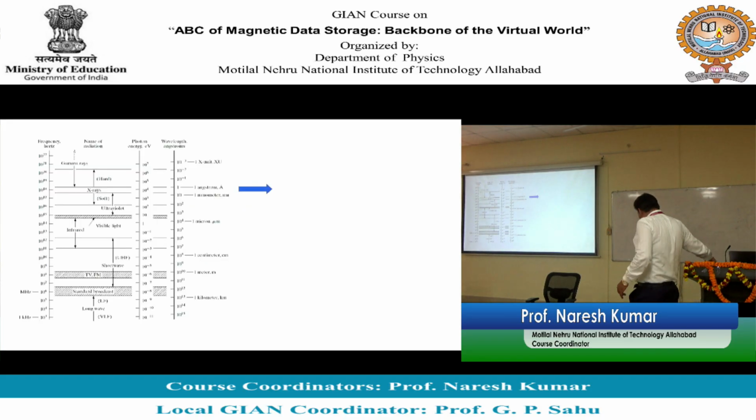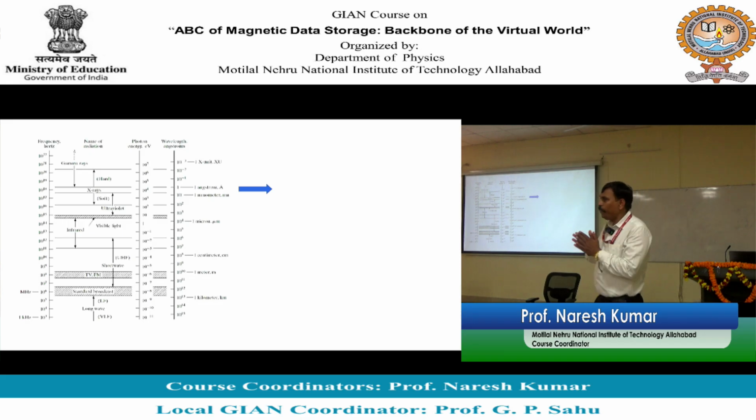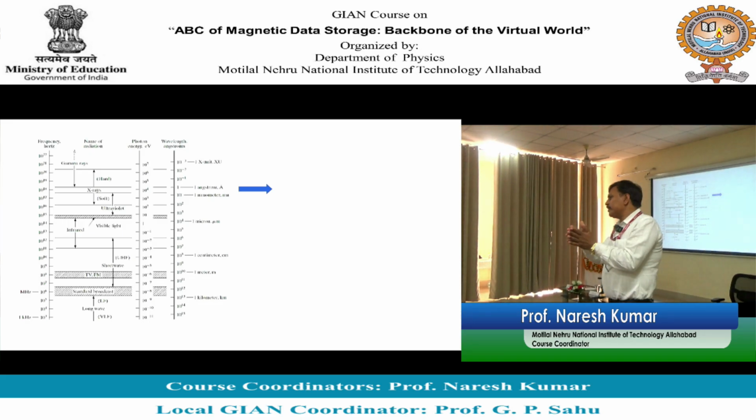Okay, so now we have checked diffraction and some very fundamentals of crystal structure. For diffraction, what is needed? The wavelength of incident light has to be of the order of the slit width. For crystalline material, the distance between 2 successive atoms is almost of the same order. What is it? 2, 3 angstrom. So if you wish to see a diffraction pattern through these crystalline materials, what should be the typical order of wavelength? It should be almost the same number.